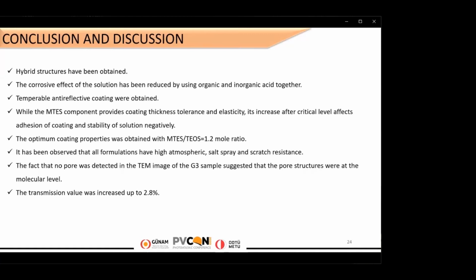Temperable anti-reflective coatings were obtained, and we saw that the MTES component provides coating thickness, tolerance, and elasticity, but its excessive increase affects coating adhesion and solution stability negatively. It's proved that the optimum MTES/TEOS mole ratio was 1.2 among all versions. Successful results were achieved from corrosion and mechanical tests for all versions.